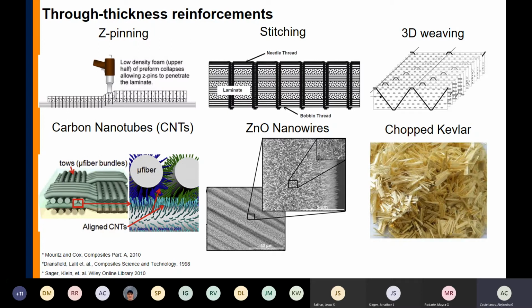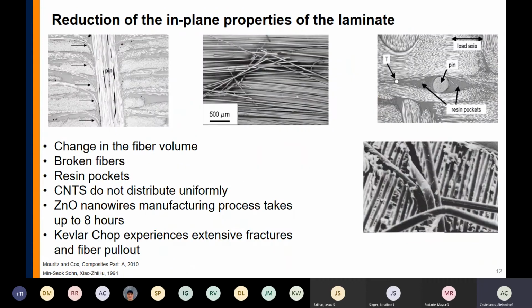Also, there is stitching, where you use a needle and a thread to completely perforate each of the layers of the composite. We also have 3D weaving, carbon nanotubes, zinc oxide nanowire, and chopped Kevlar. So there have been a bunch of studies with this, to prevent that separation, to reinforce that interlaminar region. But again, one of the problems with all of these methods is that they reduce the in-plane mechanical properties of your composite. So why is that?